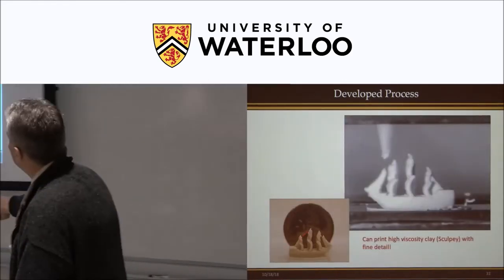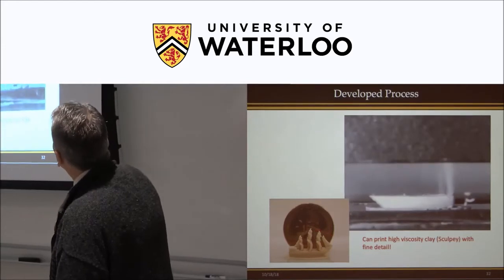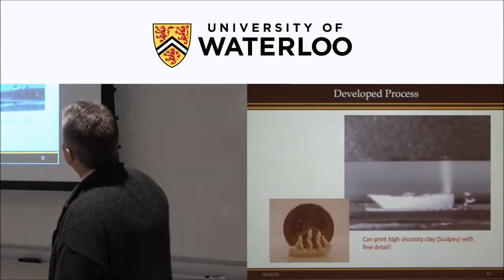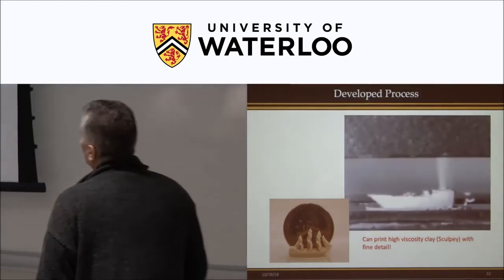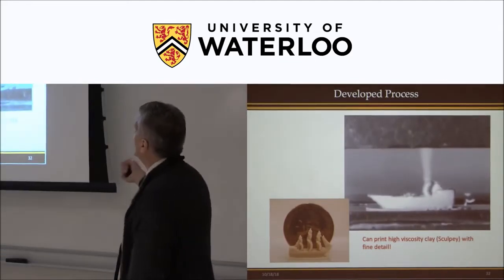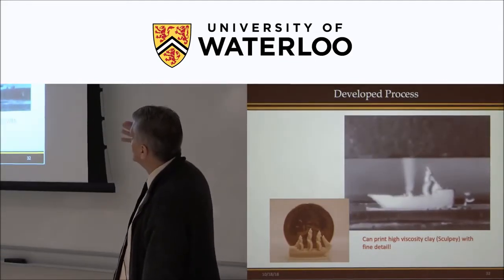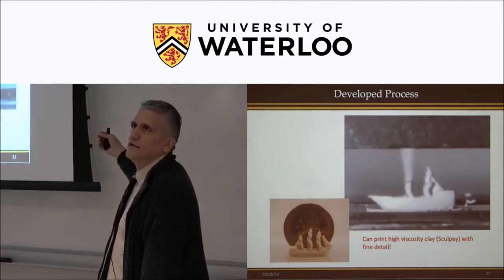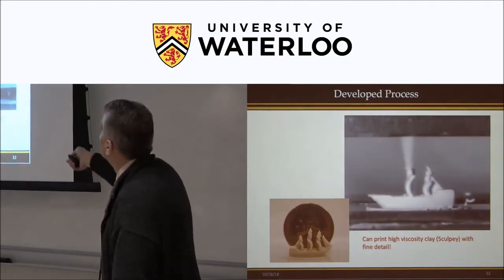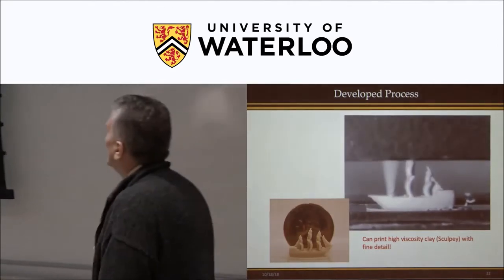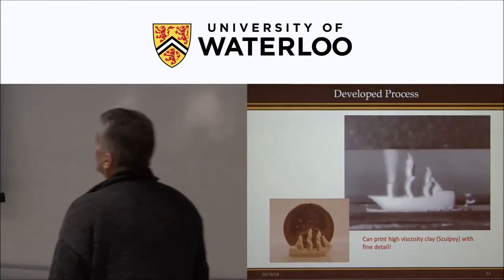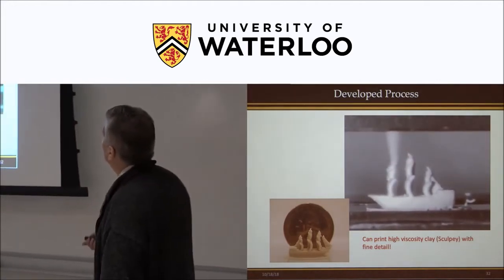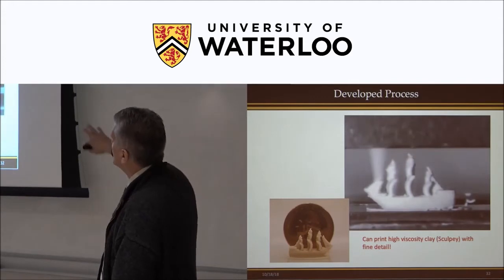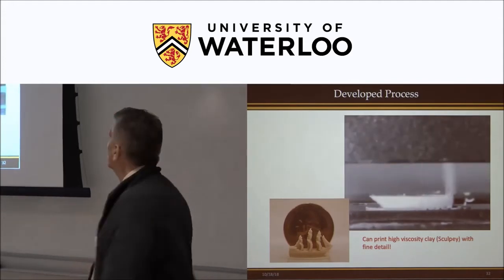You see the scale here, that's a US quarter. This is a little sailing ship printed with Sculpey clay. And when that comes out, there's no UV or anything. That's just a highly viscous clay. It has a yield point, so once it comes out, it stays in that form. The nozzle size is about 500 microns, about a half millimeter. There's no viscous printer that could print anything like that.